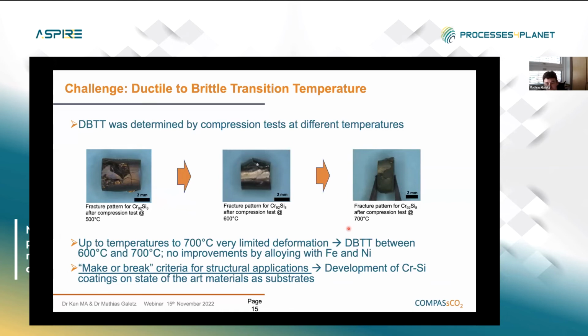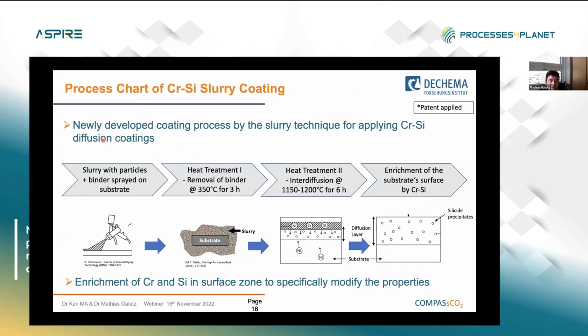So we also tried improvements that were promising from the literature by alloying with iron and nickel, but so far we couldn't significantly decrease this ductile to brittle transition temperature. And literally it's a make or break criterion for structural applications. So we went another way, to apply this as a coating, which is shown here.